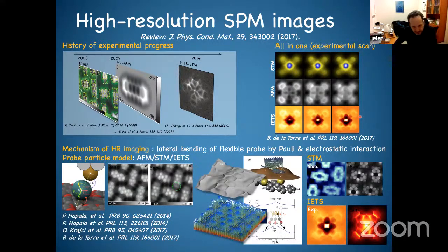Not only that, we showed in 2017 that all these three channels can be acquired at the same time. This is the paper we published, where for the first time we acquired all three channels simultaneously. This proves that the mechanism behind reaching this submolecular resolution is the same for all these three channels. We also developed the model, which is now commonly accepted as an explanation of what is behind this imaging. It's not only a model which explains what is there, but also a simulation toolkit with which we can simulate these images. You see the experimental data taken in our lab, and this is the simulation, a comparison of simulation and experiment for STM, AFM, and IETS.